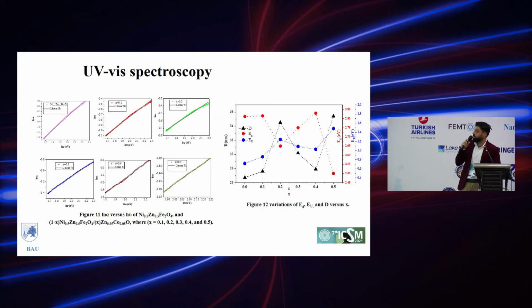So we show the logarithmic plot of the absorption coefficient versus the energy. And from these plots, we can determine the Urbach energy, which is an indication of the degree of distortion in the band structure. As shown in the graph here, we show the variation of the band gap energy in red and the Urbach energy in blue and the grain size in black.